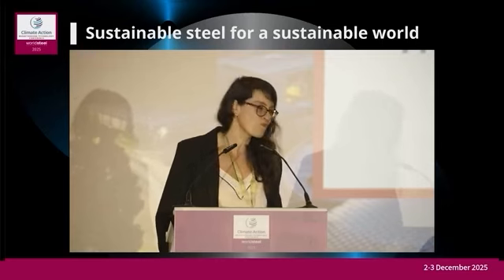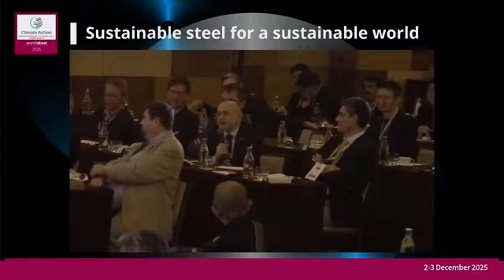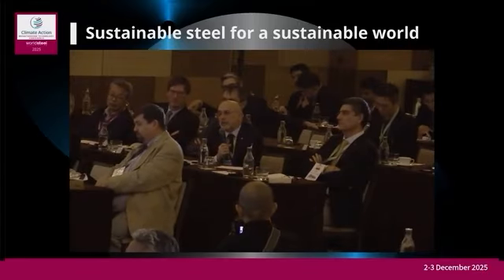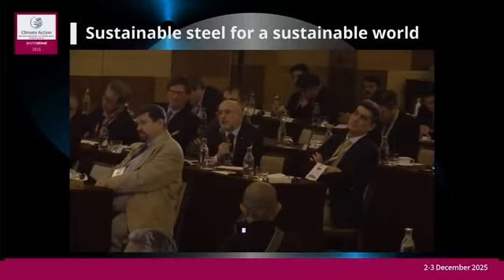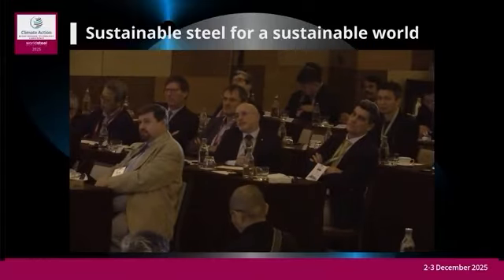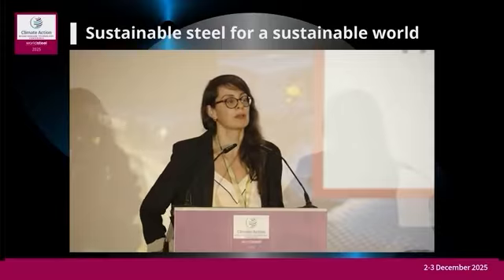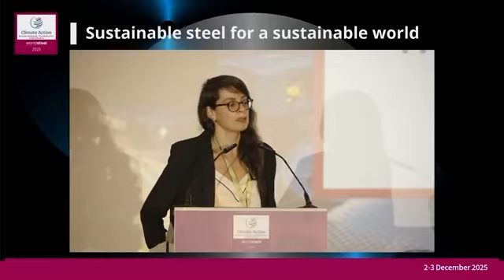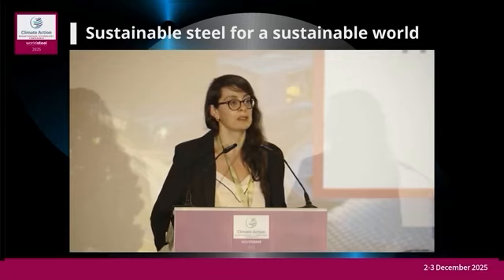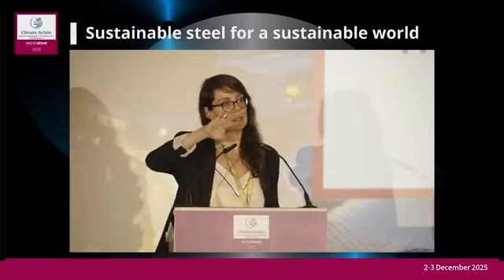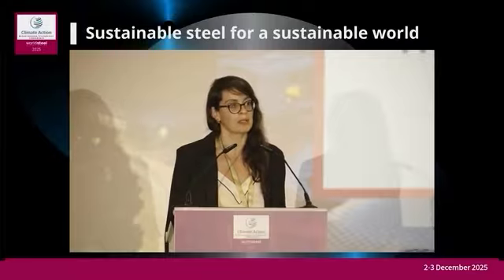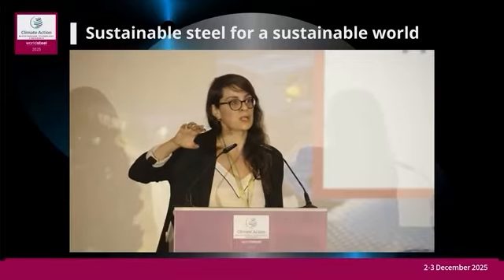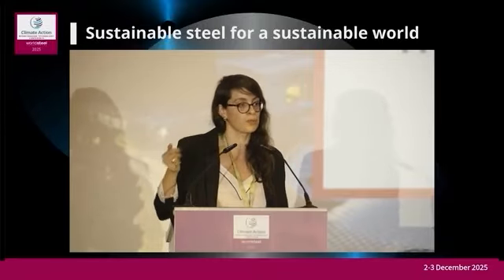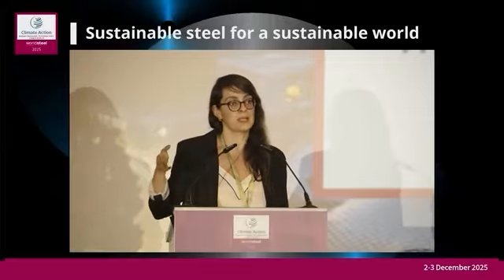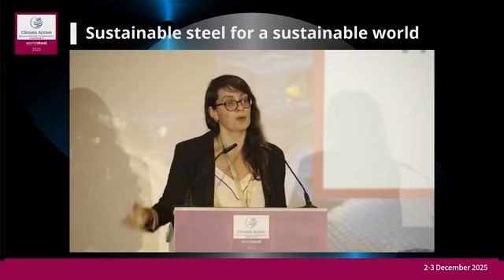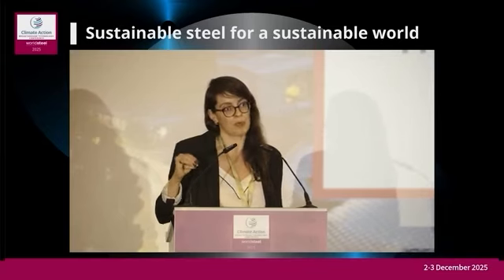There is another question, just one row behind. Have you analyzed the possibility of contamination of the steel, of the iron, with the sodium? Let's say, how much sodium you can lose with the product? In the product or during the recovery of it? In the product, together with the iron. Yeah, so we evaluated that with the chemical separation that we are doing, the sodium that is still with the iron is extracted with the chemical separation. And after the chemical separation, we insert the chemical that we are using, which is sodium hydroxide, straight into the electrochemical cell, and then we recover the sodium back. Our goal is to reach, in the iron itself, below 0.2% of sodium.